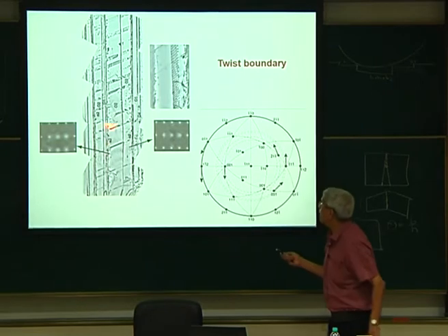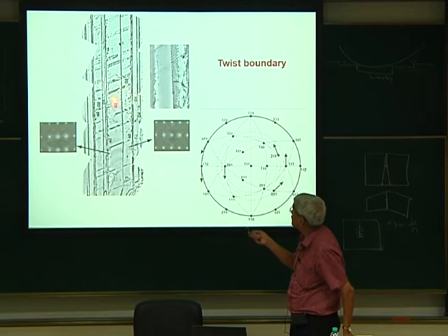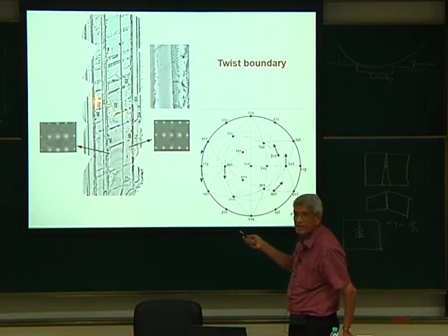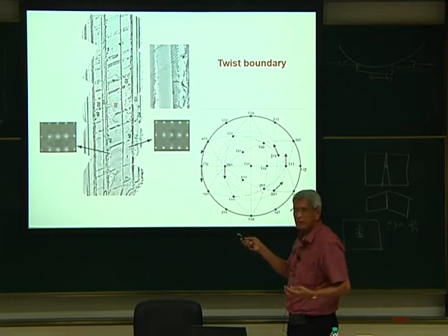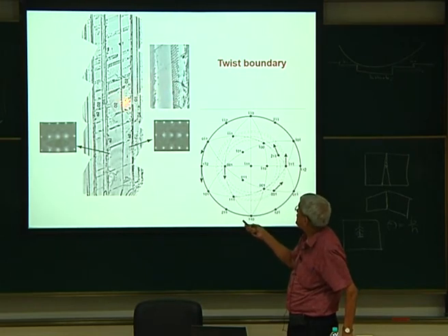Okay. This is the microstructure, where in this region as well as in this region, it is the same variant, but there is a boundary which comes in between them. Both sides look the same, like a grain, but with one boundary coming in between. If I tilt it, immediately I can see that two sets of dislocations are present. This is one, another one is not present very clearly. I will show it later, in another tilt condition it could be seen.